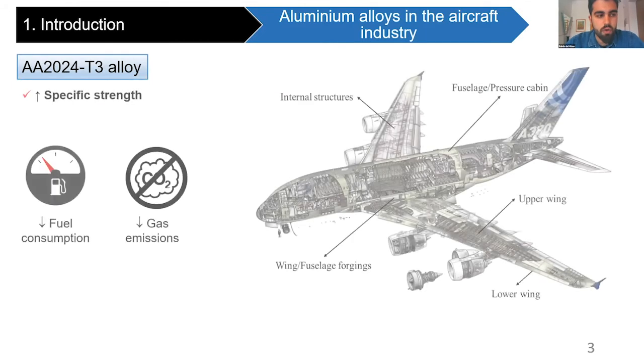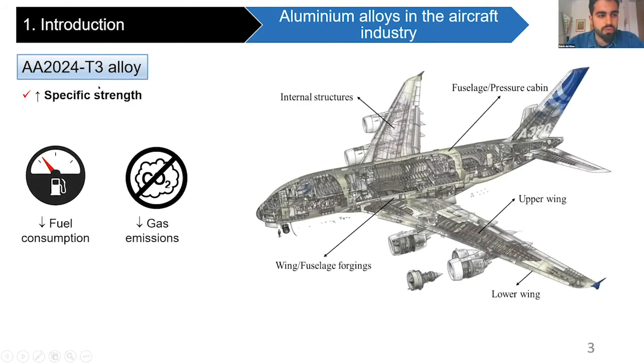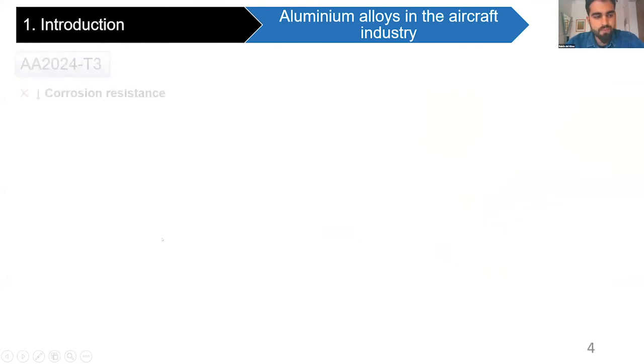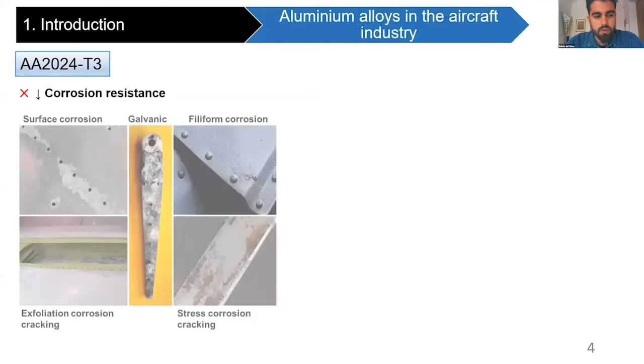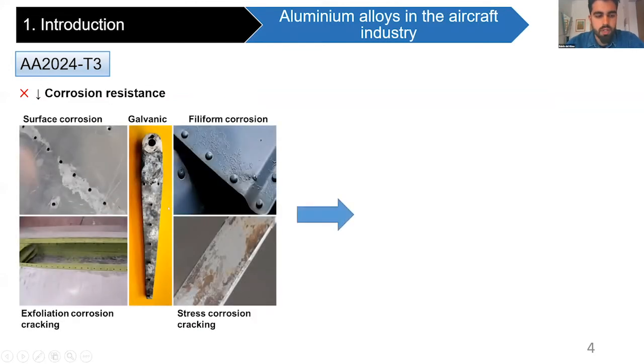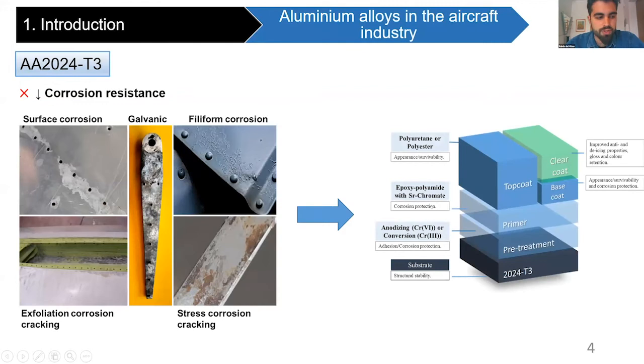First of all, I'd like to highlight that the most widely used aluminum alloy in the aircraft industry is 2024-T3 aluminum alloy. This is due to its high specific strength, which allows decreasing fuel consumption and gas emission during the aircraft service life. However, the main limitation of this alloy is its low corrosion resistance. For this reason, this alloy is usually surface treated with a multi-layered protection scheme, which consists of a pretreatment, a primer layer, and a mono or bilayered paint system, depending on its application.